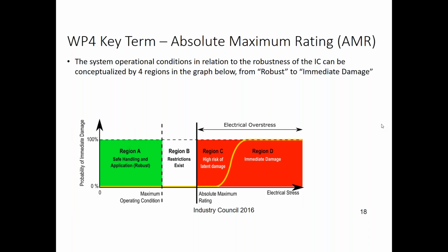Another question. For those dealing with oxide breakdowns in devices, does the minimum voltage have to be supplied for electrical field breakdown to occur before current then flows and damages the device? The current is what actually damages the device. Yes, I agree with that. So the high field itself doesn't necessarily produce permanent damage. Of course, here we're talking about a specific failure mode of a specific material more than anything else. But to get permanent damage, there has to be some local heating, so there will be current which flows. That's a good question, a correct interpretation, I think.